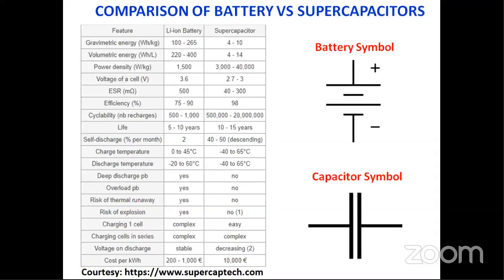There are not only the differences in energy and power, there are huge differences between the lithium battery and the supercapacitor. Of course, the gravimetric energy of the lithium battery lies between 100 to 265 watt hour per kg, but in the practical case it is nearly 170, 180 watt hour per kg. But in supercapacitors, gravimetric means you are getting that energy based on the weight of your material. Here it is 4 to 10 watt hour per kg.